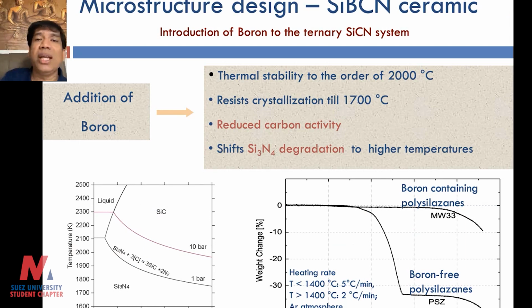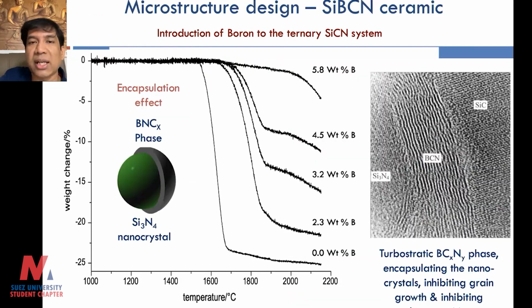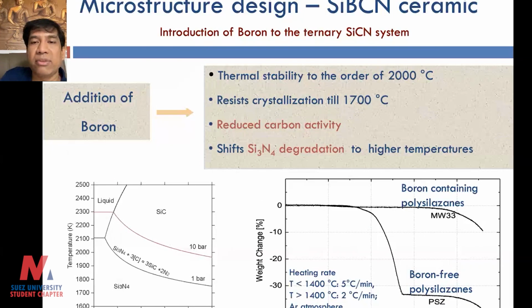For example, we have worked on boron-modified silicon carbonitrides, and these boron-modified silicon carbonitrides are very stable till 2000 degrees Celsius, very ideal for extremely high temperature applications. We have done thermodynamic calculations.